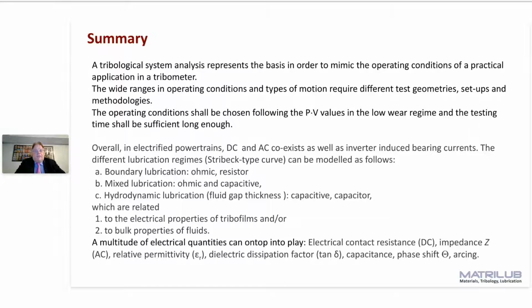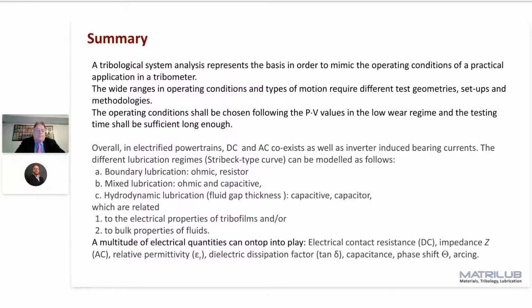And second, the electrical properties of the total tribo system are composed of those from the tribofilm and those from the fluid, and they depend on top on the temperature. So we have now a multitude of quantities that come into play: electrical contact resistance, DC, impedance, AC, relative permittivity, dielectric, the capacitance, phase shifts, tangent delta, including arcing, where first we need those tools in our test equipment, and second, it is not fully clear what is good and bad for the application.